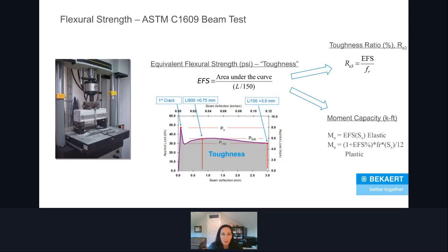And this is a beam test where you take a 6x6 by 20 inch beam section, you put it into 4-point bending, and you measure load and displacement with an LVDT. So you're going to get some kind of graphic curve that looks something like this image here in this center. Right? And in this ASTM C1609 test, you're going to extract 3 key data points: the first crack stress, or the modulus of rupture, as well as at the L/600 displacement and L/150 displacement.